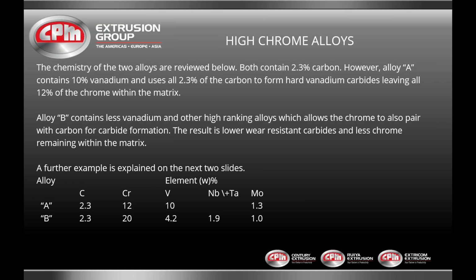Alloy B contains less vanadium and other high-ranking alloys, which allows the chrome to also pair with carbon for carbide formation. The result is a lower wear-resistant carbide and less chrome remaining within the matrix for corrosion resistance. Further examples on the next two slides.